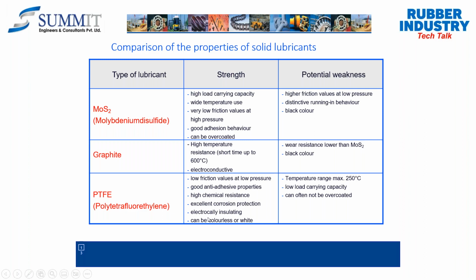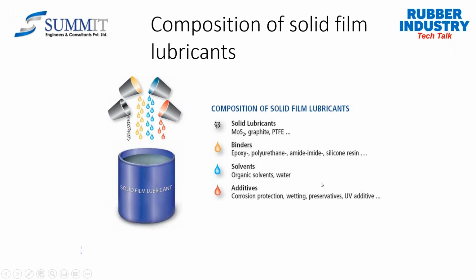So if we make color coding for the O-rings, then it could be very easy for you to identify them. The composition of the solid film lubricants is: the solid lubricants, which are normally available in powder form, MoS2 (molybdenum disulfide), graphite, PTFE. Then certain binders, the solvents, which could be organic solvents as well as water, and the additives.